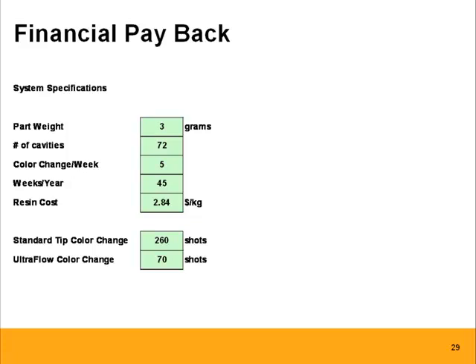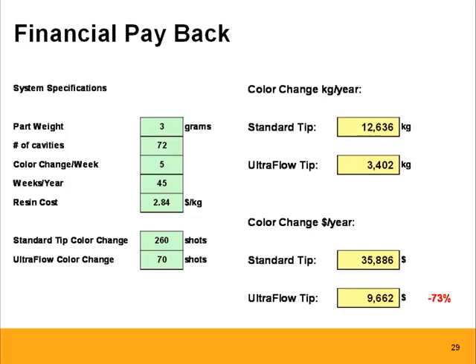And then just as a reference, a standard color change, 260 shots, and UltraFlow, or by other means achieved enhanced color change, 70 shots. Now you look at what that does to you in regards to resin savings and dollar savings, the numbers become pretty significant. A standard tip, for example, in this case, we used up over the year 12,000 kilograms just for color change. All scrap material, nothing you can do with that. With an UltraFlow tip, about 3,000 kilograms.